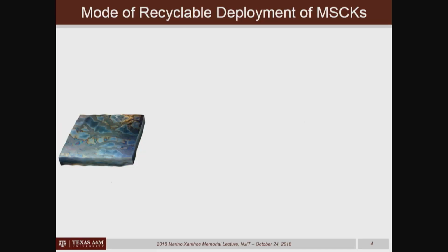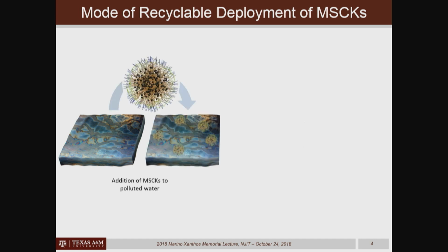Okay, so we thought, well, there might be a nanotechnological solution to this. We thought if there's a contaminated water system, then we could put out into that aqueous system a dispersant. And this project started after the Deepwater Horizon oil spill had occurred in the Gulf of Mexico back in 2010. And one of the techniques to deal with the vast amount of oil that couldn't be boomed and pumped was to put out dispersants. And my thought was, if there's a polluted environment and then we're putting out surfactant molecules to disperse the residual oil, we're adding pollution after pollution, and it's maybe not the best solution.